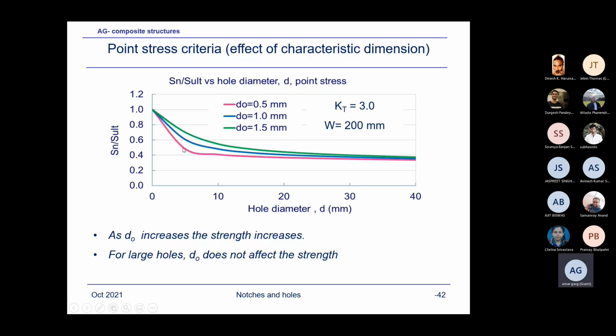Suppose you use a very small characteristic dimension like 0.5. That means you will be too conservative in your predictions, so unnecessarily you will be putting a weight penalty on the structure. So one has to be cautious when you are trying to predict the residual strength, that the right value of characteristic dimension should be used.